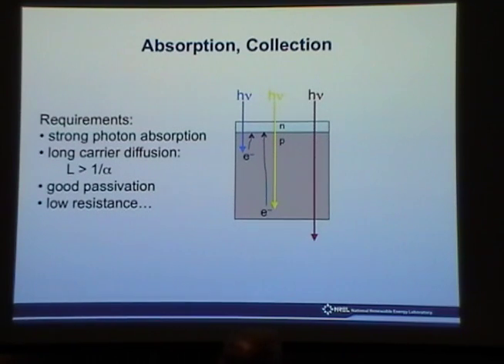So you want strong photon absorption. You want long carrier diffusion, meaning electron hole pairs that are created at the back of the cell, you need them to diffuse to the junction. If they don't diffuse to the junction, they don't get collected and they're lost. So you can have beautiful absorption, but you're not collecting it. If you have a low mobility, for example, or you have a low lifetime, you have a lot of defects, and you get carrier recombination before it can be collected by the junction. You want good passivation. It's easy to lose electron hole pairs at the front and back interfaces, and so you want what we call passivation, but really it means chemically or with a different material terminating dangling bonds so that you don't get extra recombination. And you want low resistance as well.